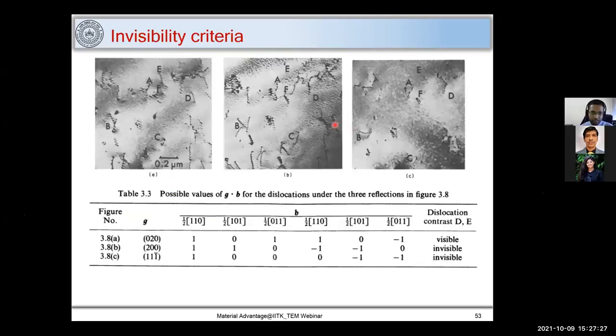Now, the invisibility criterion is used to identify the Burgers vector. Here, I would like you to pay attention to these two dislocations, which are E here and D here. In this first image, you can see these two dislocations, E and D. I know the crystal structure, so this is for copper. I find out the different G vectors, and I also find out the different Burgers vectors. Then I take the dot product of G and B and find out their values. When G dot B becomes 0, these dislocations will vanish, or they will be invisible.